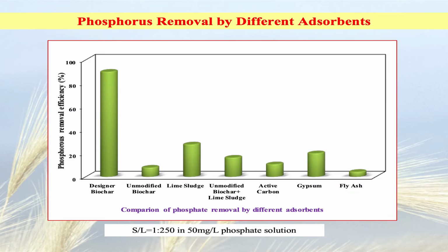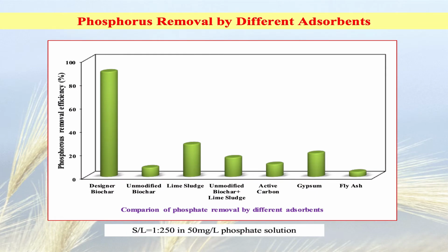Here, I just give you a sample, using one of the designed biochars to compare with the most commonly used phosphate adsorbents. You can see this is the designed biochar. If you have a phosphorus solution of less than 10 milligram per liter, this designed biochar can remove 100%. This comparison is conducted under a 50 milligram per liter phosphate solution. You can see the designed biochar can remove 90% of the phosphate. It's much higher than non-modified biochar, at like 5%. Also, this is much higher than lime sludge, gypsum, fly ash, or activated carbon.